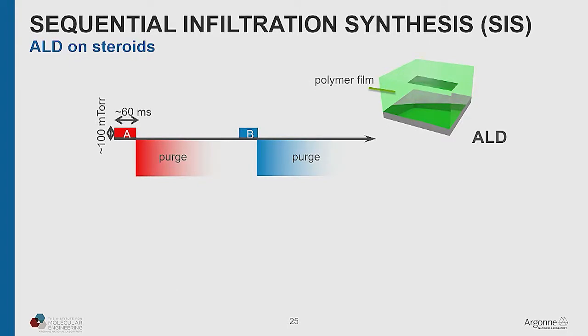SIS, which is the technique that we invented at Argonne, is related to atomic layer deposition, but it's qualitatively different in a way that I'll describe here. So in this case, we're dealing with a substrate like a polymer film. And you can do atomic layer deposition, ALD, on a polymer film. So you would pulse in a little bit of reactant A, sort of millisecond scale pulses and millitorr, so not very much vapor, purge it out with something like nitrogen and then a little pulse of B, and you could decorate the top surface of a polymer film this way with something inorganic, like an inorganic oxide.